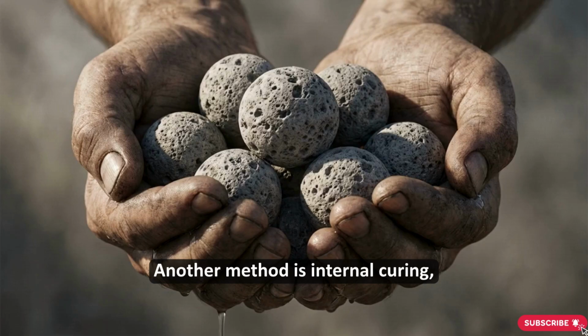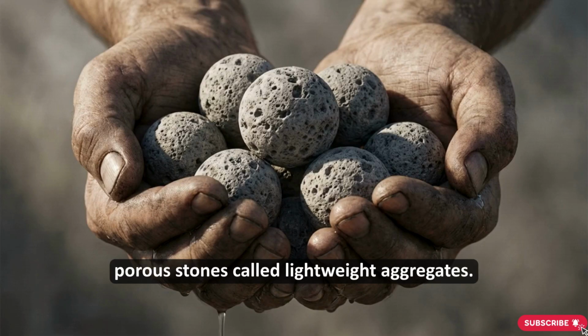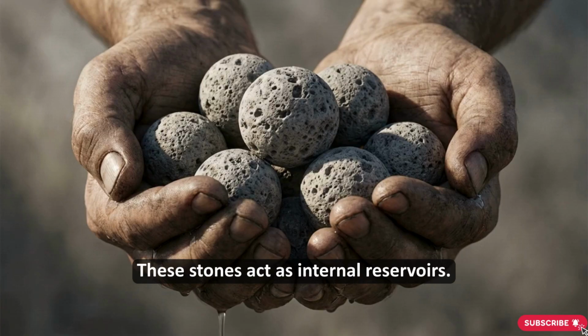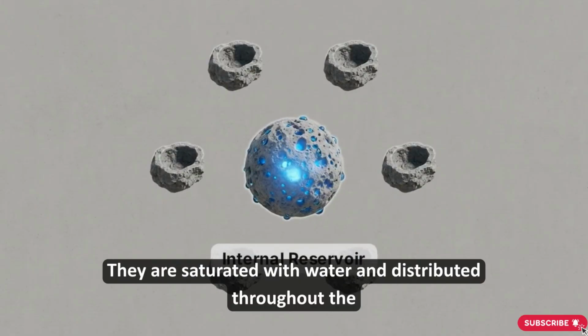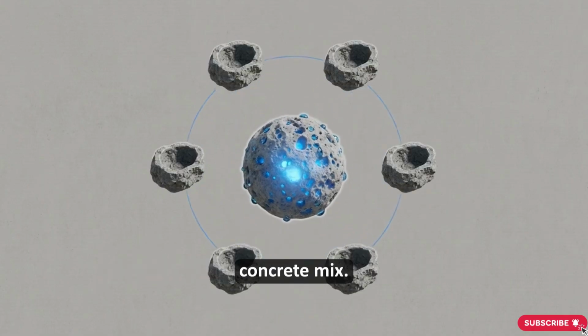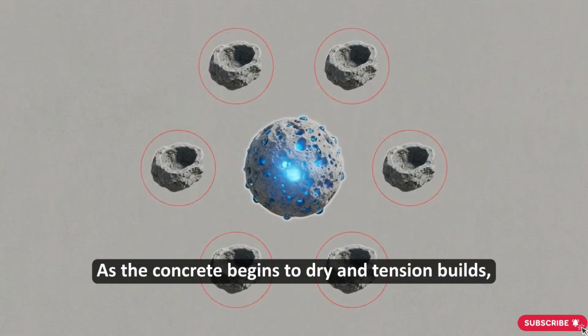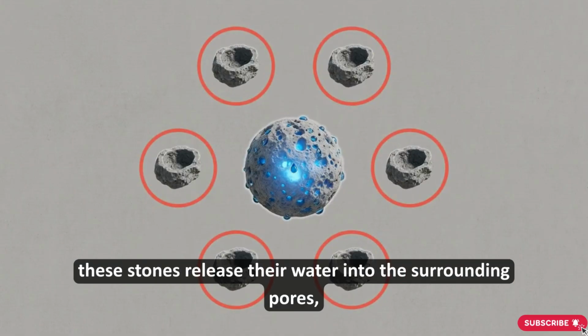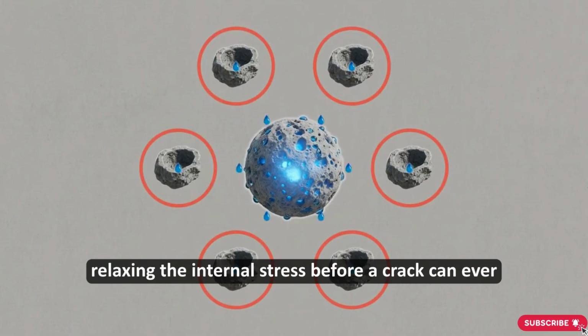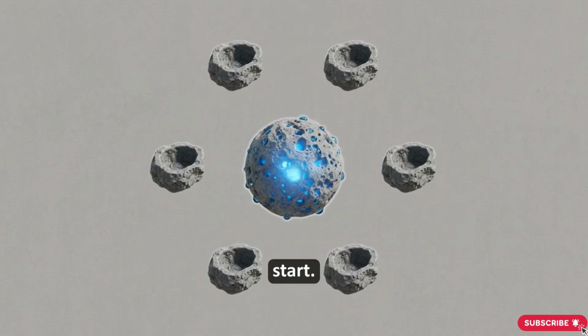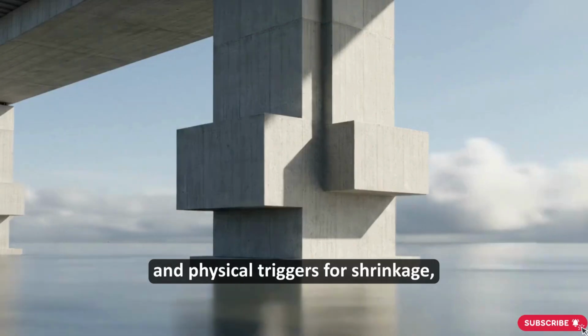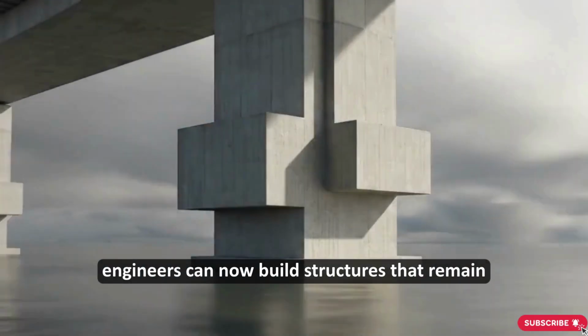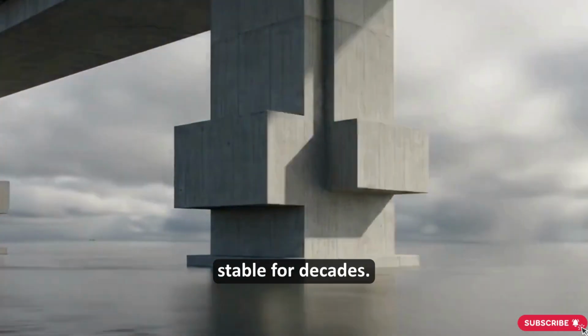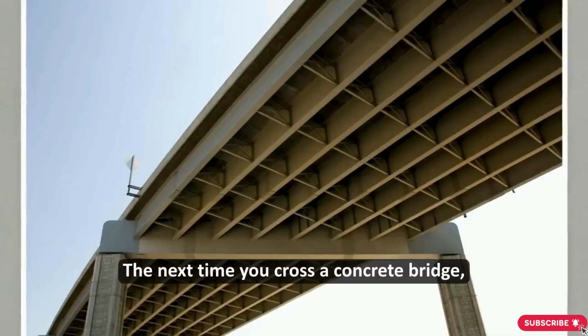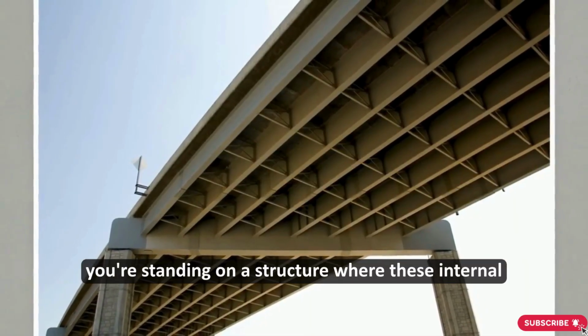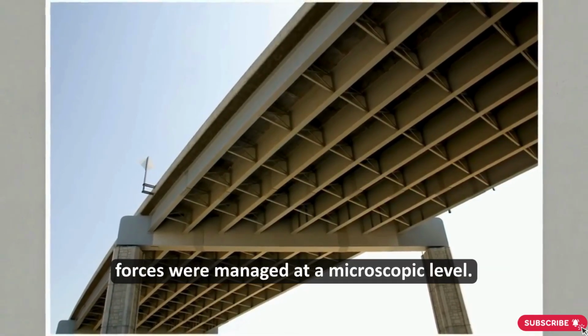Another method is internal curing, which uses pre-wetted porous stones called lightweight aggregates. These stones act as internal reservoirs. They are saturated with water and distributed throughout the concrete mix. As the concrete begins to dry and tension builds, these stones release their water into the surrounding pores, relaxing the internal stress before a crack can ever start. By identifying the specific physical triggers for shrinkage, engineers can now build structures that remain stable for decades. The next time you cross a concrete bridge, you're standing on a structure where these internal forces were managed at a microscopic level.